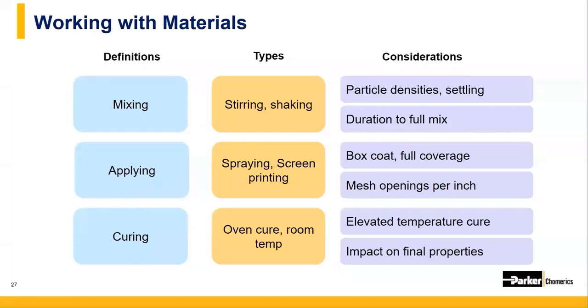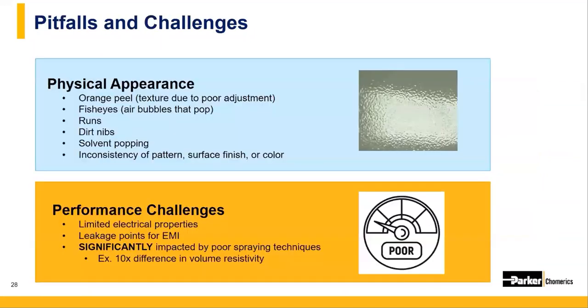Oftentimes, coatings will need to cure for a short period of time at room temperature to allow for the solvent evaporation before being cured at a higher temperature for those final mechanical properties. It's equally important to discuss what to do versus what not to do and why. There are pitfalls and challenges to applying a proper coat of conductive coatings and inks.